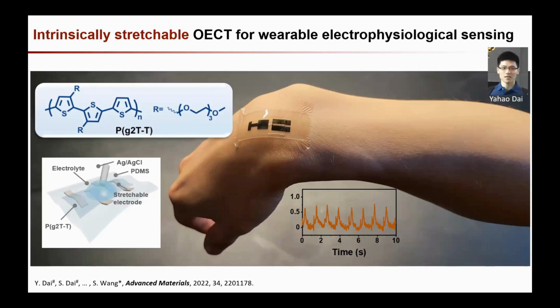So this enables this polymer structure to deform to the stretching level of 200% strain. It's 3 times of the original length without forming any crack. And then using this polymer, we further made it into a fully stretchable OECT-based electrophysiological sensor. And we have demonstrated its use on the deforming, like a raised area for measuring the ECG signal, electrocardiogram. And because of the stretchable property, even when the skin is deforming, the recording function is not really getting affected. Okay, so this is showing what stretchable property can help us.